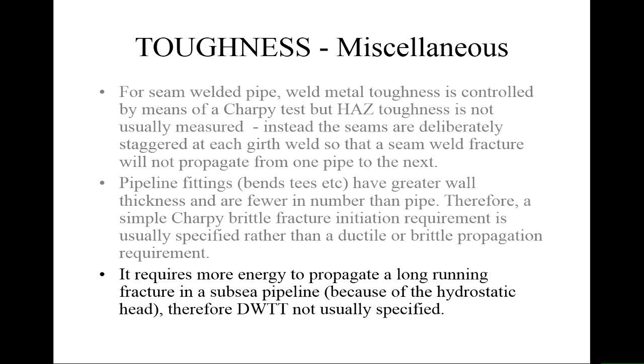Is that particular to a specific depth, or is it? I have not seen anybody talking about this when the depth is more than about 100 metres, but yes, I think there is. If you're in the splash zone and you're in the shallow depths, then there are all sorts of other questions, and I'm sure the specifications are much more complicated in that case. But for the basic pipe material on the seabed, generally not an issue. Again, we do the Charpy test for material quality, and that should cover everything. That's the idea, I think.